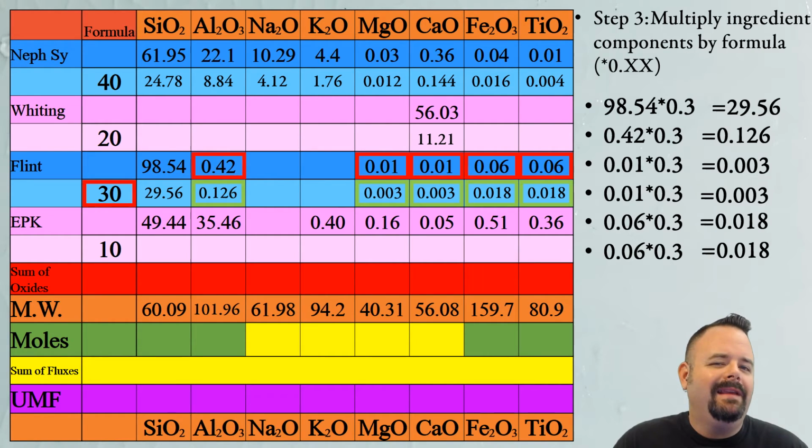So this sometimes leads to a discrepancy between numbers calculated by hand versus numbers done by a spreadsheet or by software, but that's okay. We often find a lot of variation in UMF numbers, especially because you could be using a different chemical analysis reference. If they run a sample on a different day, the analysis is slightly different. So you're going to find small variations, and that's all right. You just don't want to see any major variations in your UMF numbers. So these all have 3 significant figures, so we're going to keep all these numbers.